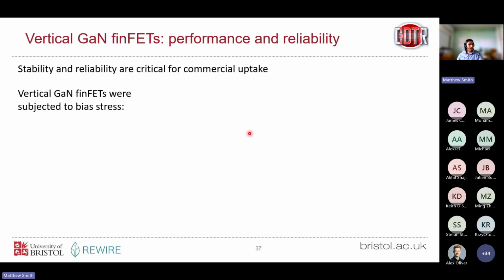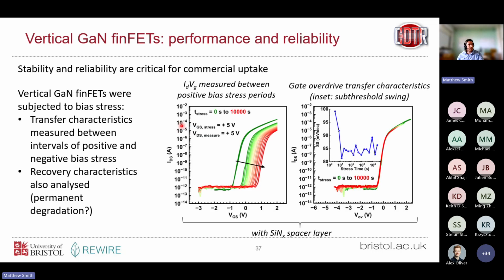Okay, so once we've made these devices with high breakdown voltage, we looked at stressing them. So this is a characteristic where we first just measure our transfer characteristic in these second generation high breakdown voltage devices, and then we stress them under bias. This is positive gate bias stress, positive drain bias, and then we remeasure the transfer characteristic intermittently during that stress phase. What we find here is that initially, this green curve, we get some threshold voltage, but then as we apply bias, that threshold voltage drifts.